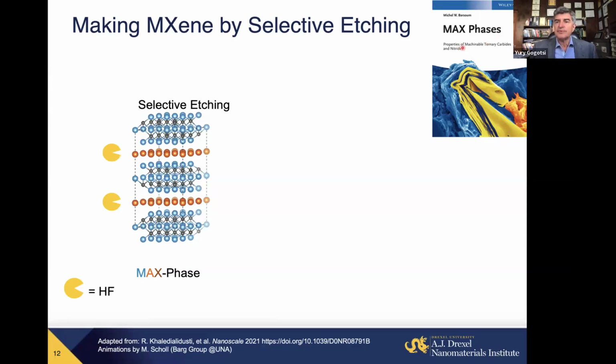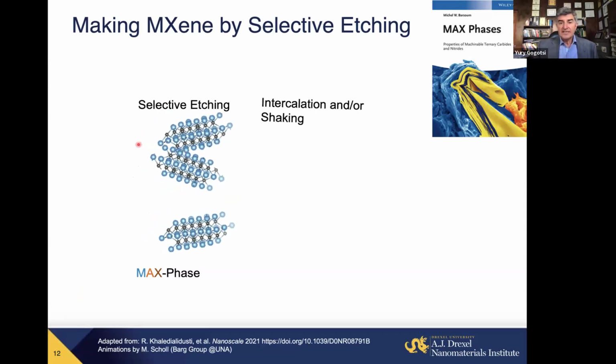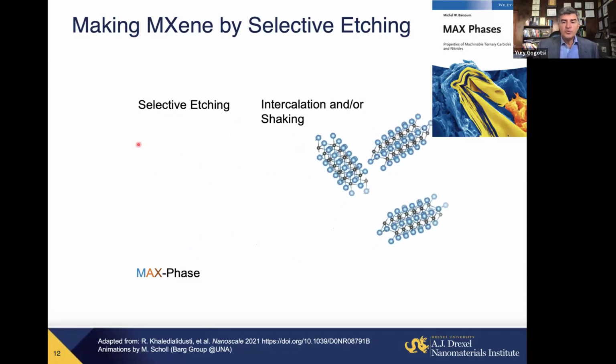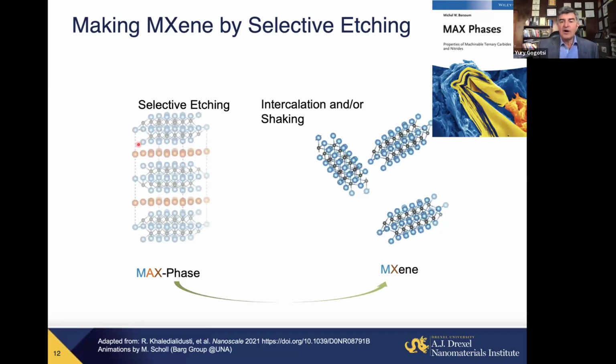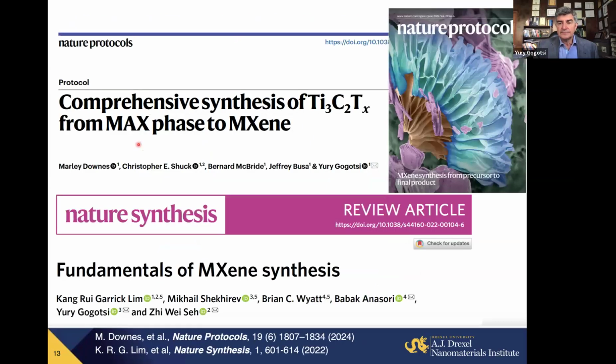My colleague at Drexel, Professor Michel Barsoum, is a leader in this field. So what we did, we chemically etched away the A element, because in these MAX phases, there was strong bonding between an A element like aluminum and a transition metal like titanium. You cannot purely mechanically separate it, unlike graphite. As a result, we got loose sheets, weakly bonded, that now can be delaminated into two-dimensional flakes.